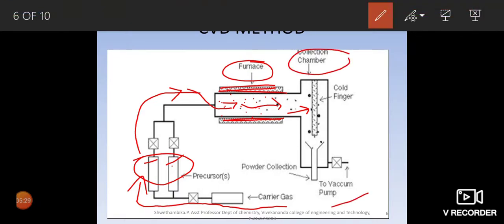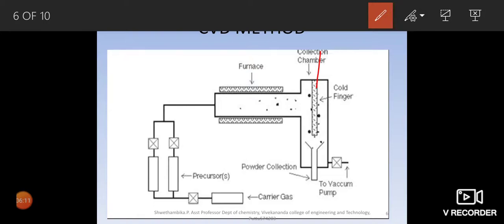Then from the cluster you are making it to enter a collection chamber. This collection chamber is always evacuated. Collection chamber is connected to a vacuum pump, that means this collection chamber is evacuated. There is no chemical or anything present inside. And then the collection chamber is fitted with a cold finger. What you call it as cold finger means it is actually a substrate which is maintained under very low temperature, that actually we use liquid nitrogen maintained temperature. Liquid nitrogen temperature is extreme cold conditions. We maintain this finger and it is always rotating.